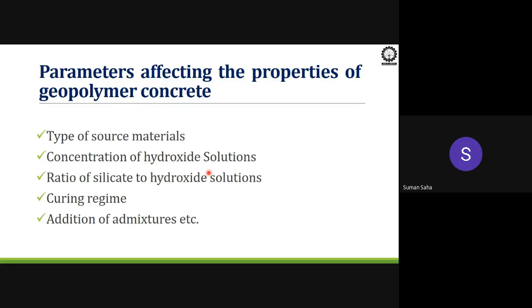And as I have told you, the combination of sodium silicate and sodium hydroxide is the best suitable combination to be used as the alkaline liquid. For that, we need to prepare this solution. Usually most of the literature will suggest to prepare the combination of this solution 24 hours before use.